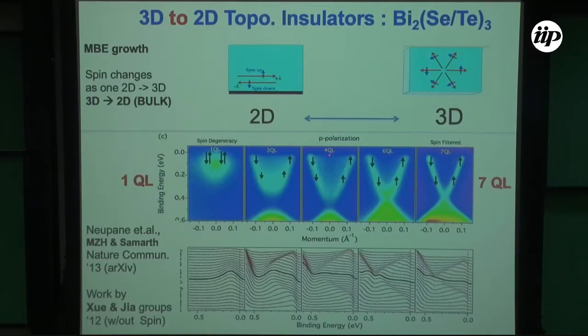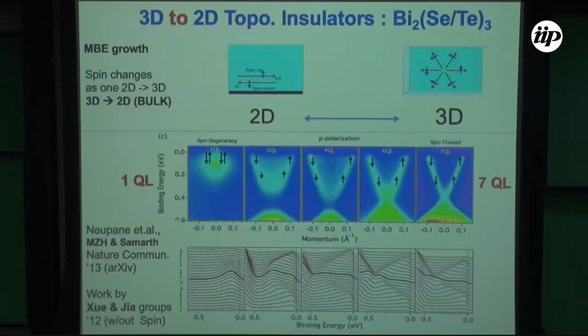Now we go back to our experiment. What happens if I have 4 nanometer, 4QL? There is a gap, right? So that means if I do ARPES on top of this sample, even though it's a multi-layer, it should look like there is a gap in the top layer, and there's no Dirac fermion. This is just a gap band structure or massive Dirac fermion.